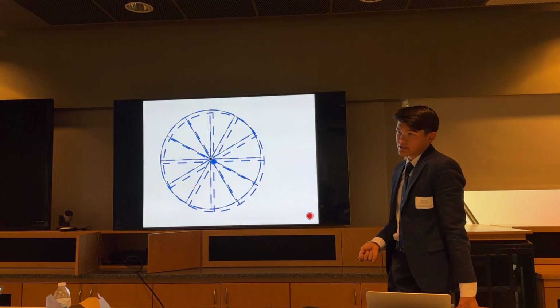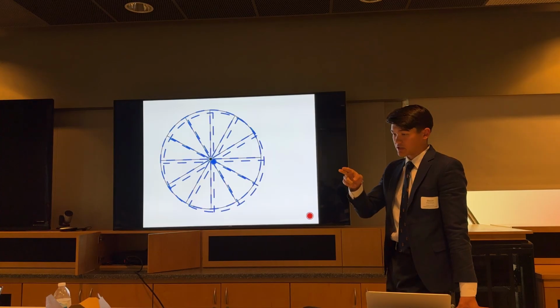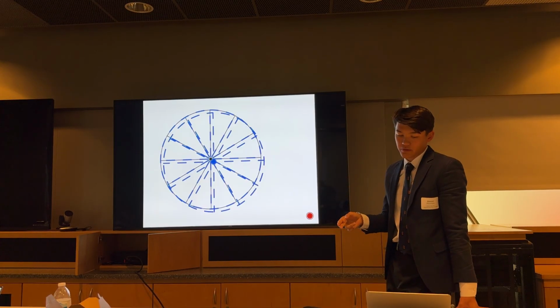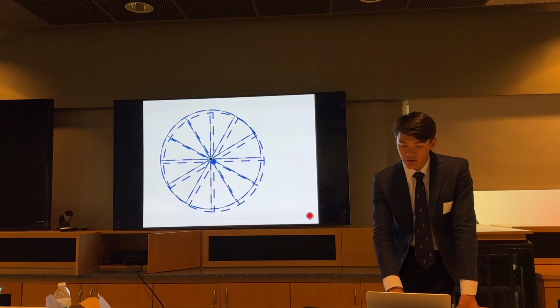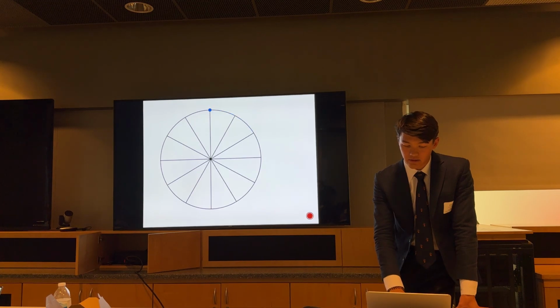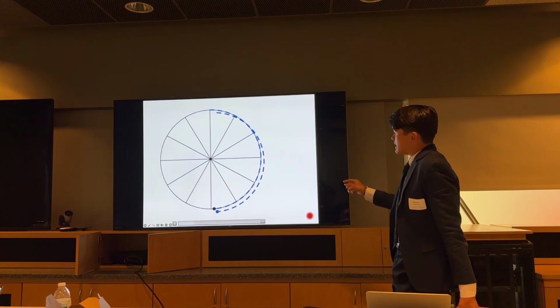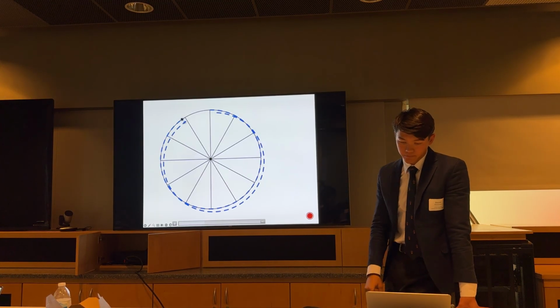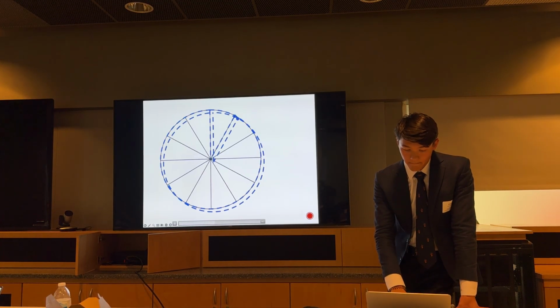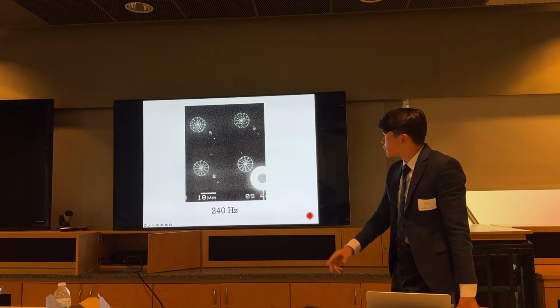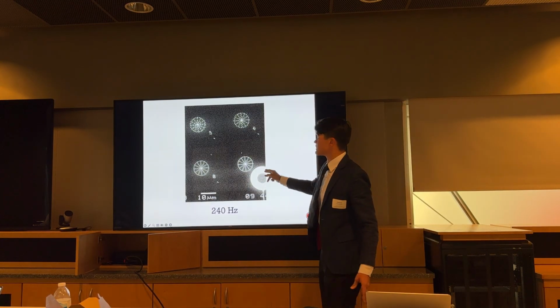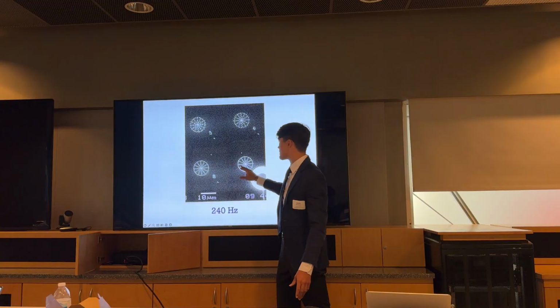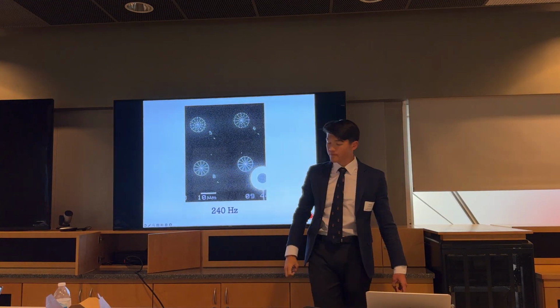And this noise appears to be a certain digital jump with a fixed frequency. So since the frequency of the noise is fixed, as you vary the speed of the beam, the resulting pattern should also change. So here's a slower beam and we can see smaller dots. So going back to this image, that's exactly what we see. This is a faster beam with longer dashes. This is a slower beam with shorter dashes.